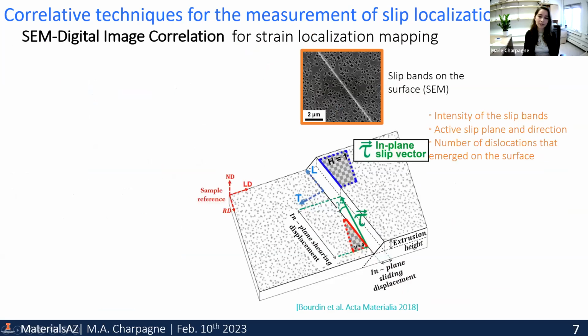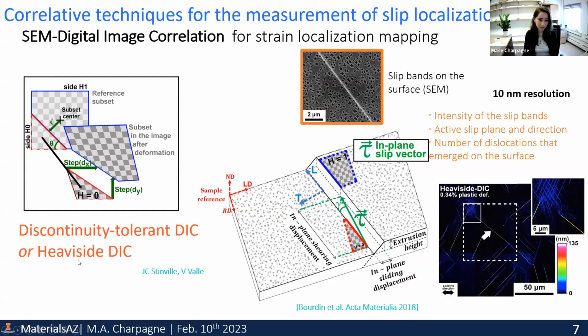And in our case, of course, we're interested in those slip bands, which we can see in secondary electrons. But from electron images, we cannot quantify how many dislocations are actually traveling in that slip band. And so with the new technique that JC developed in collaboration with the French team, they have made these DIC codes tolerant to discontinuities. As you have a slip band that forms here, you now get a discontinuity in your strain field. And the new technique that they developed, which is called Heaviside DIC, allows us to actually quantify the height of this step and how wide it is.